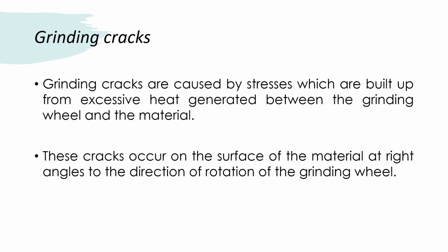Grinding cracks. The grinding cracks are caused by stresses which are built up from excessive heat generated in between the grinding wheel and the material. So these cracks occur on the surface of the material at right angle to the direction of rotation of the grinding wheel.